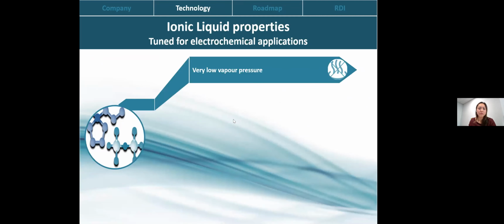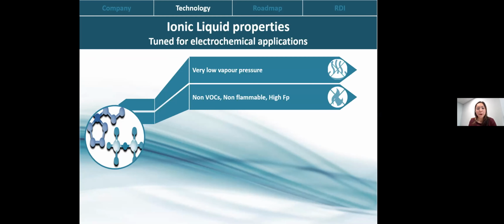The electrochemical applications of ionic liquids, that is important. The properties that are important for the electrochemical applications are that they have very low vapor pressure. So you can see that in batteries, sometimes we have swelling that leads to explosion and stuff like this. It's because there is a gas pressure buildup, which later I will talk more about in one of the case studies. And then it is also non-volatile, so non-flammable, and they have very high flash points of more than 100, 200 degrees.